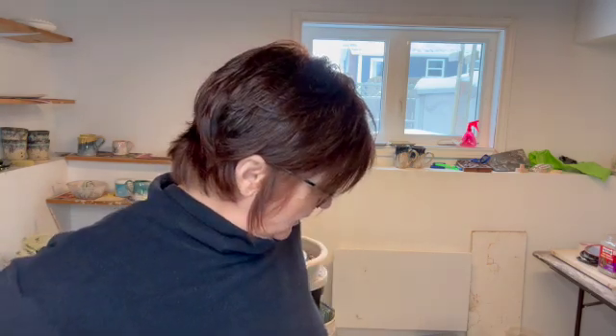So this kiln went to cone 6, held for 5 minutes, and then a slow cool down to 1900 for half an hour. And Tucker's mid smooth stone clay, I think, on most of it. I don't think there's any speckled clay in here.